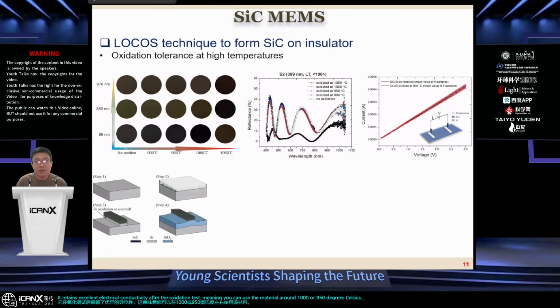And with this property, we found that you cannot oxidize silicon carbide at 950 degrees C, meaning you can selectively oxidize silicon underneath the silicon carbide, because you can easily oxidize silicon using either dry oxidation or wet oxidation. And that's a property that we utilize to form silicon carbide on insulator, very similar to silicon on insulator, and we call it SiCoI, silicon carbide on insulator.